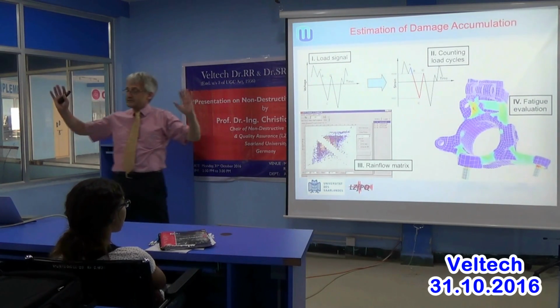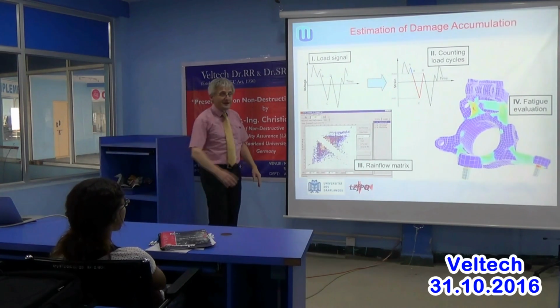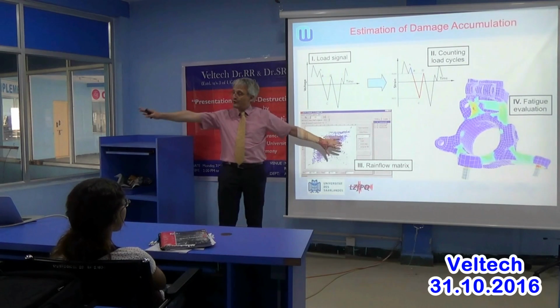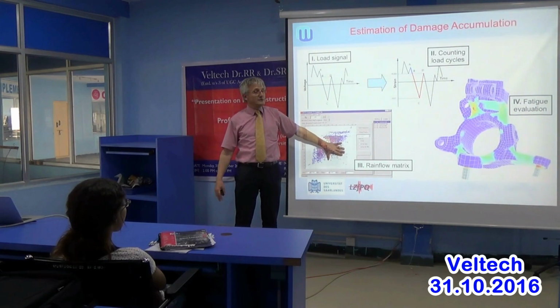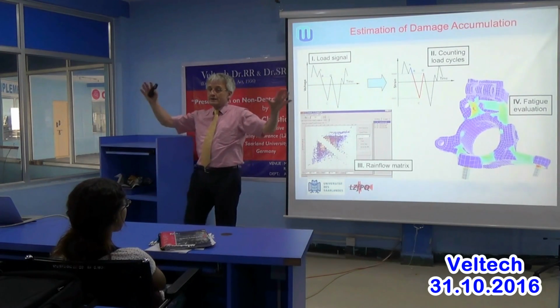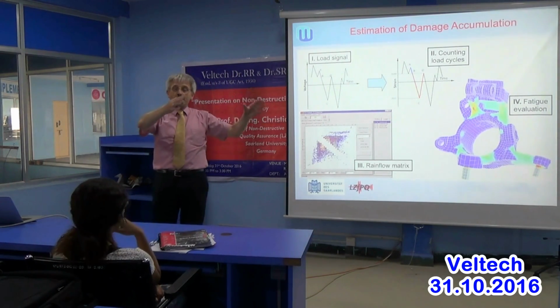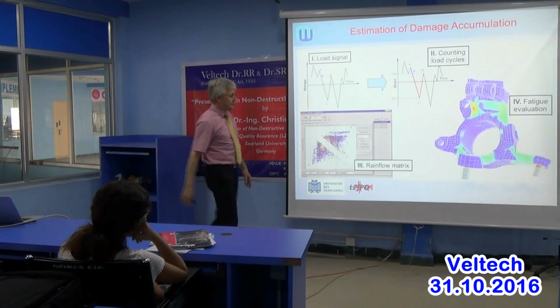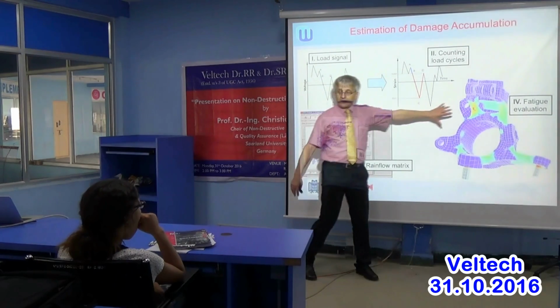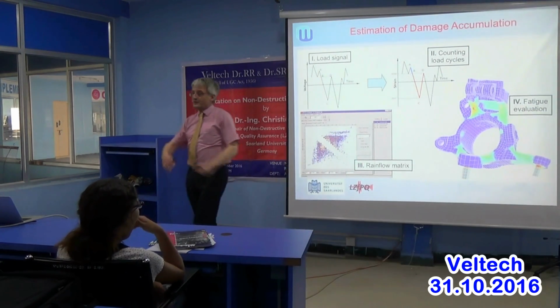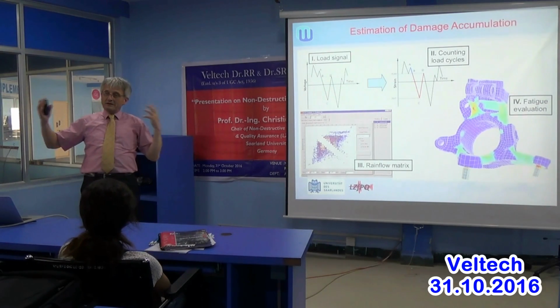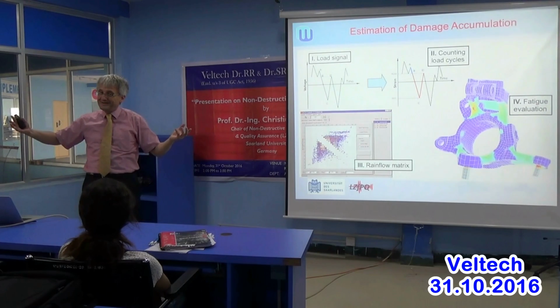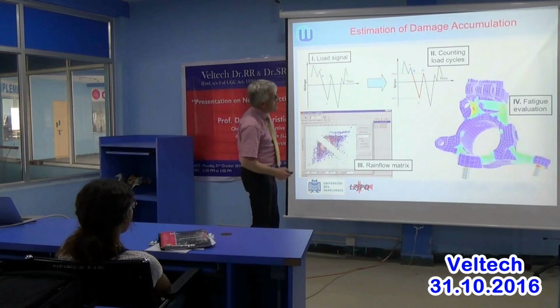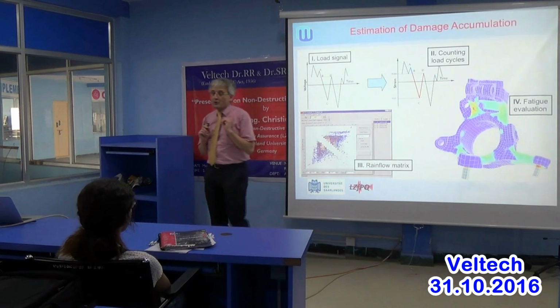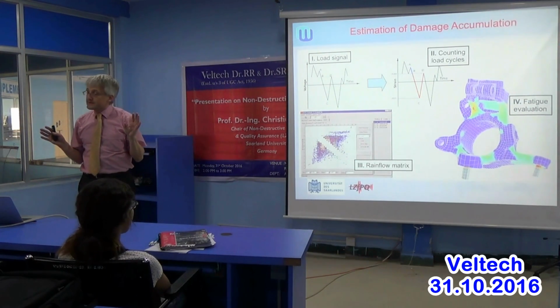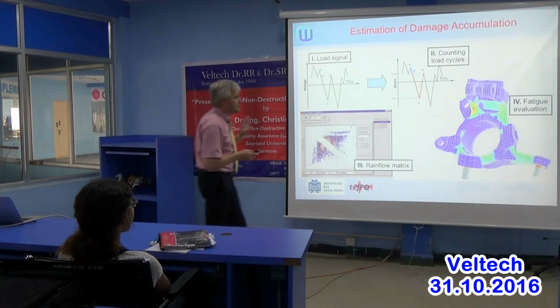Or if you ride bikes is, by the way, one of the most excellent examples you can take. So each of us could get on a bike, we could monitor how you bike, and each of us would get a certain pattern. And now we want to know how long is the bike going to last, depending on the way you ride. And this one we can do by calculation, we can do by simulation, and we will get a fatigue life calculated. And the fatigue life is unfortunately, if you do a test, the test will be quite different. But at least what it tells you is there are areas where your damage accumulates more, and there are areas where your damage accumulates less. And it's in those areas where damage accumulates more, where you have to look.